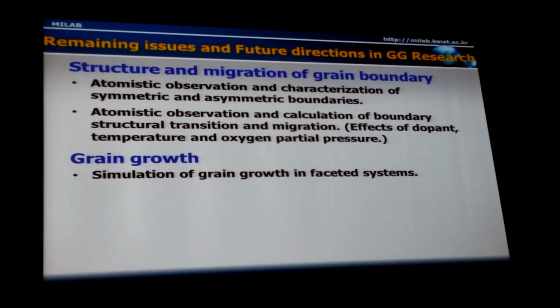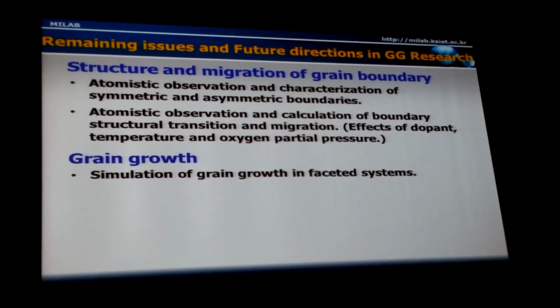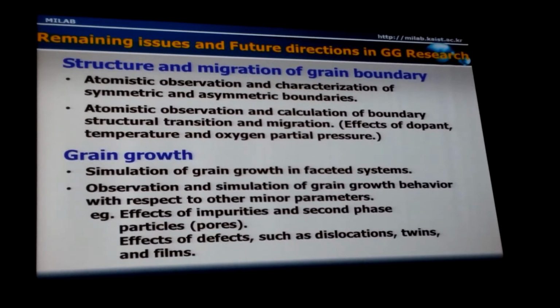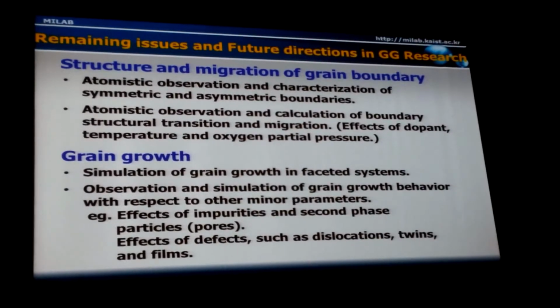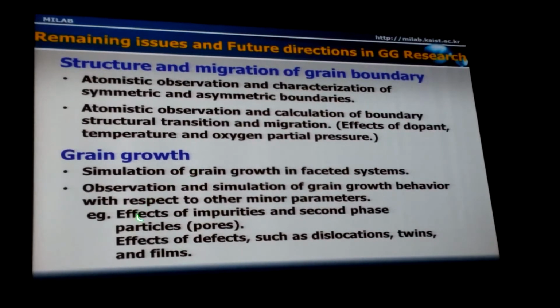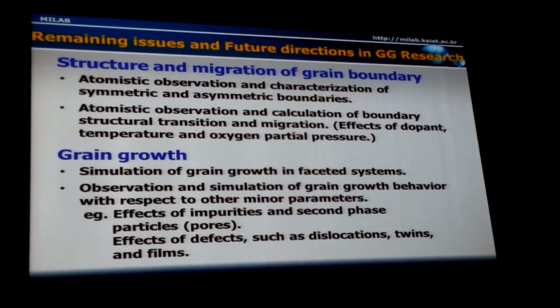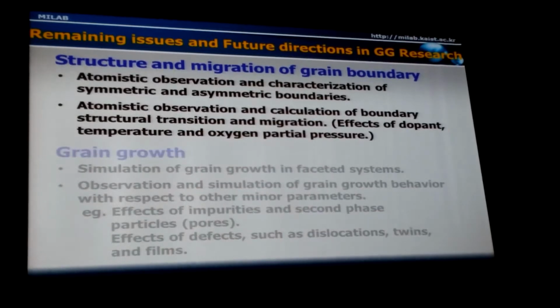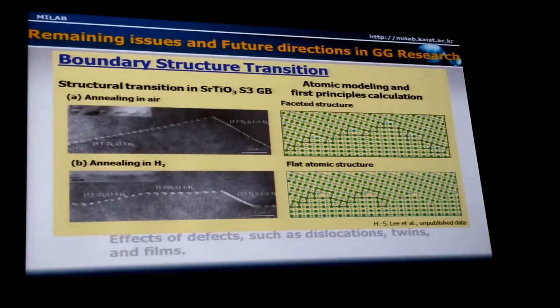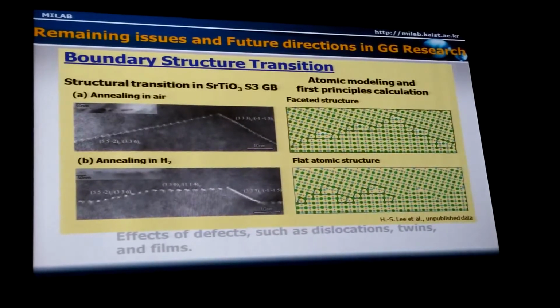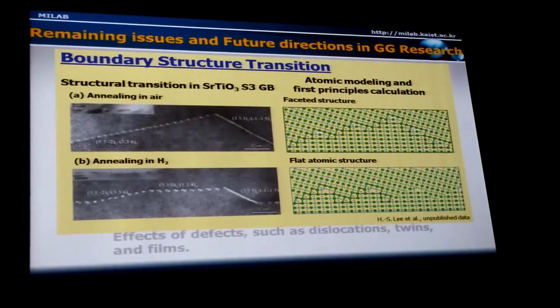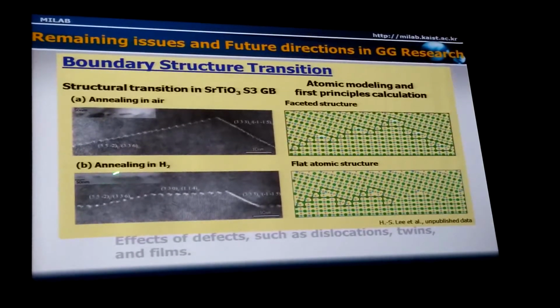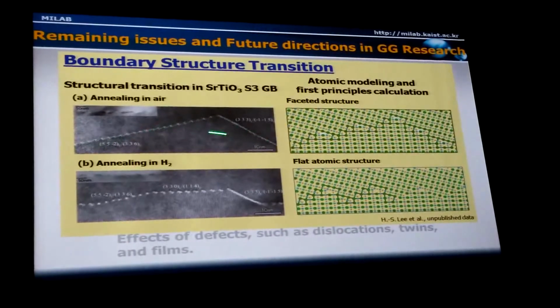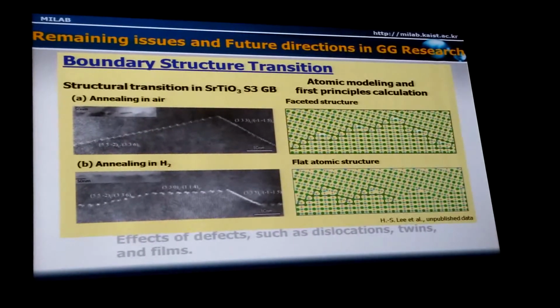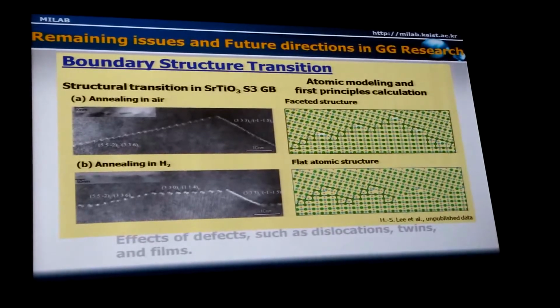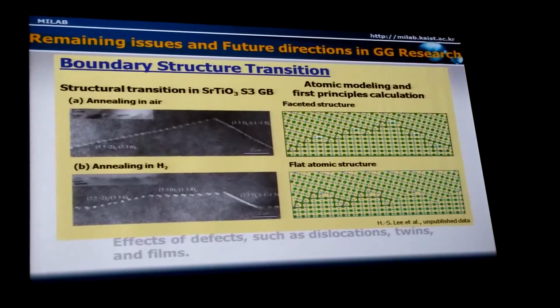And in the area of grain growth, simulation of grain growth, of course, in faceted systems, in particular in solid state, and also the observation and simulation of grain growth behavior with respect to other minor parameters, for example, impurities, second phase particles, and dislocations and twins, something like that. So, for example, the boundary structure transition observation has already been done in a few groups. For example, Professor Ikuhara and Dr. Lee observed the grain boundary structure at different oxygen partial pressures, and also did atomic modeling and first principles calculation, as shown in this viewgraph.